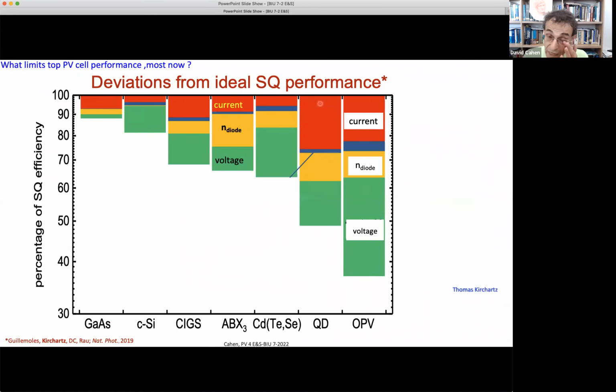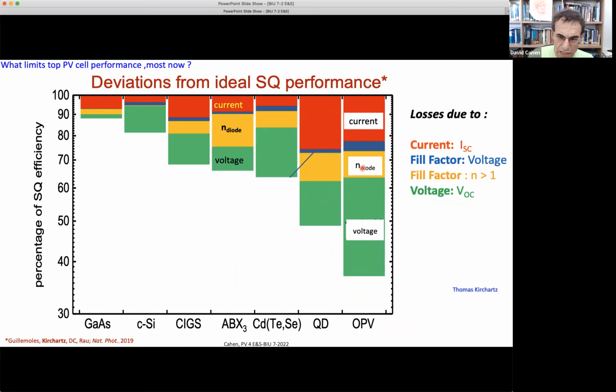So the deviations from the ideal Shockley-Queisser performance for various types of solar cells, where the red is the current and the green is the voltage, and the brown-orange is essentially what gives you a deviation from ideal diode behavior. And what you see, the fill factor, is that for gallium arsenide, it's the current that is the main problem. For silicon, that's not the case. For silicon, it's the voltage, and you can understand it. It's an indirect semiconductor. Nothing you can do about it. For cadmium telluride selenide, which is a commercial cell, it has 7% of the world market. Yes. It's definitely the voltage.